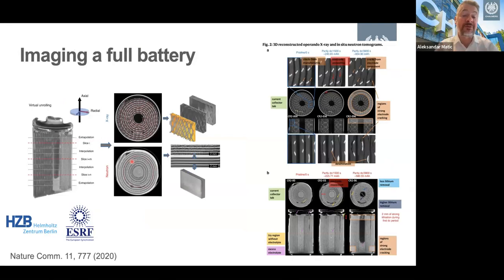Here's one example of work done at Helmholtz Zentrum in Berlin and at ESRF, where they look at a battery cell. In this case, it's a lithium cell, but it's not a rechargeable cell, where they look with both neutrons and X-rays. And you can immediately see the difference in the contrast because neutrons will have mainly the contrast from the electrolytes, from the hydrogens, whereas X-rays have more the contrast from the heavy elements. So in this case, we have the three electrodes. They are rolled up in this kind of cylindrical cell shape. And you can see, we can directly see the different layers. And with cycling, we can follow what happens. In this case, there were signs of delamination, electrolyte drying out, and so on as one of the failure mechanisms.